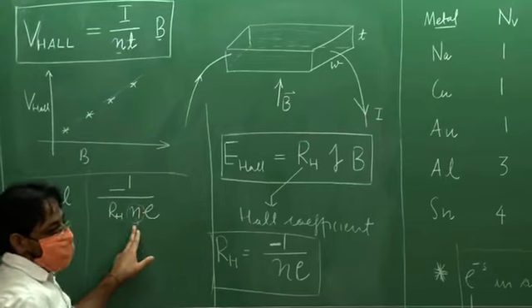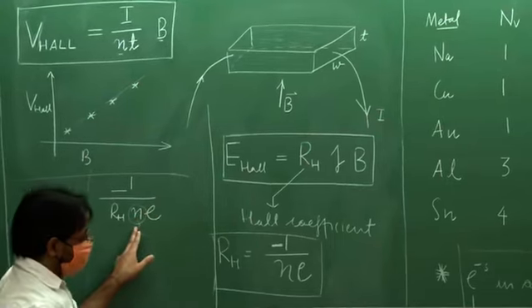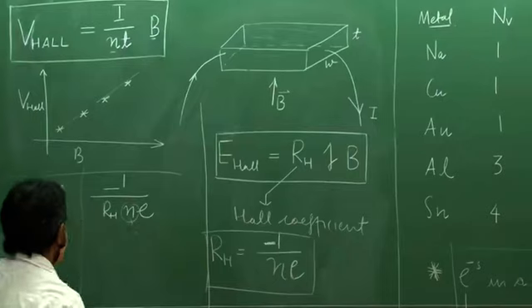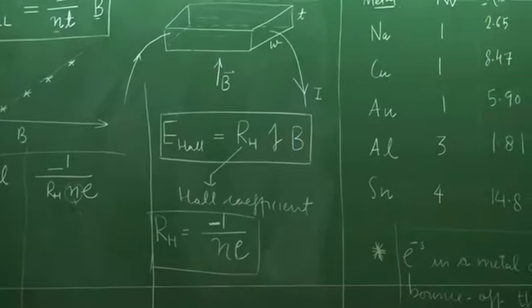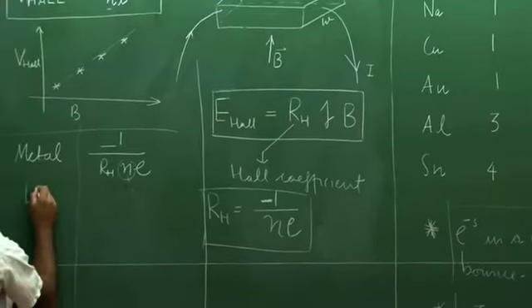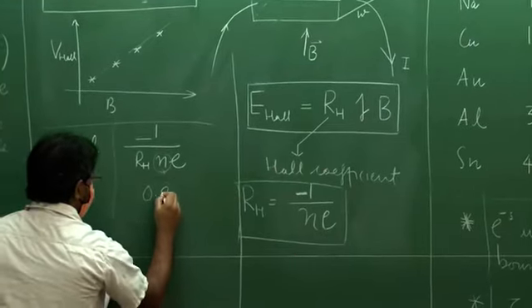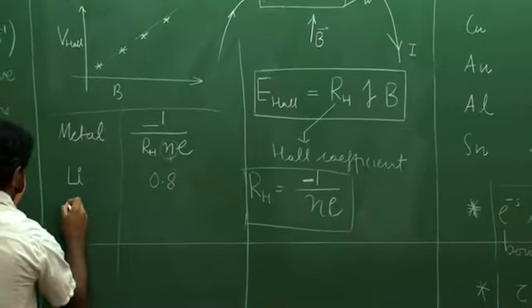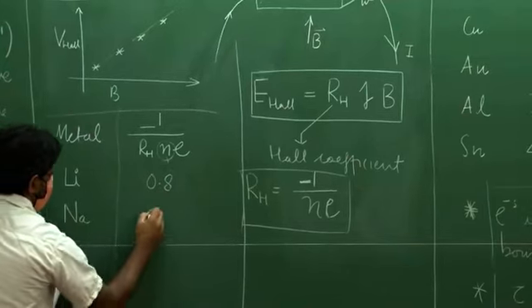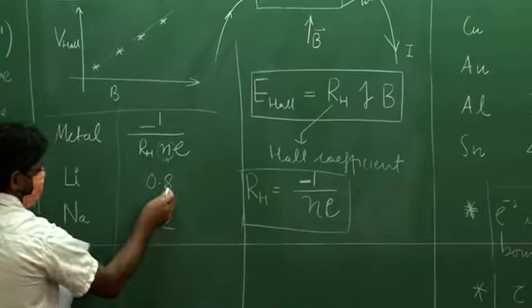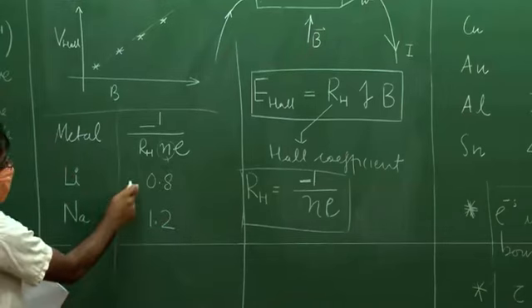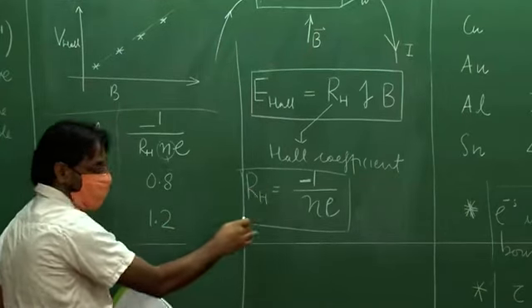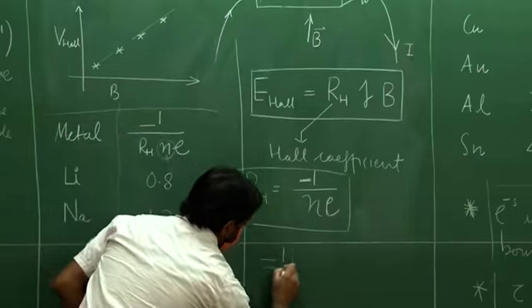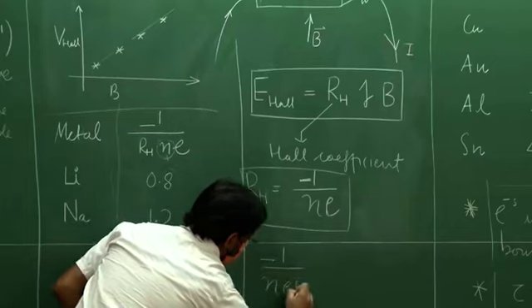So we are trying to see whether it comes out to be 1 or not, right? This should come out to be 1 if everything is right. So what we get is, for lithium, this number is 0.8. For sodium, this number is 1.2, and they are fairly close to 1, because we expect this quantity to come out to be 1, isn't it? So this quantity, minus 1 over N E RH, should be equal to 1.